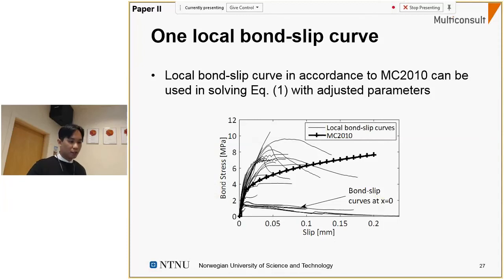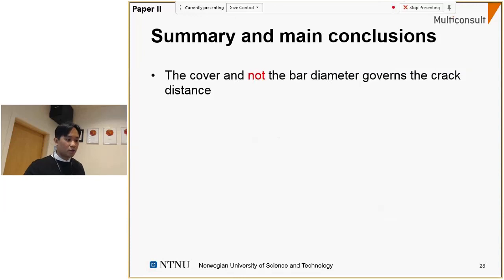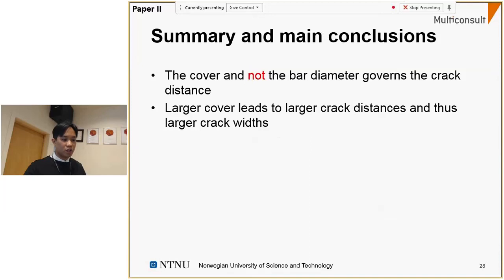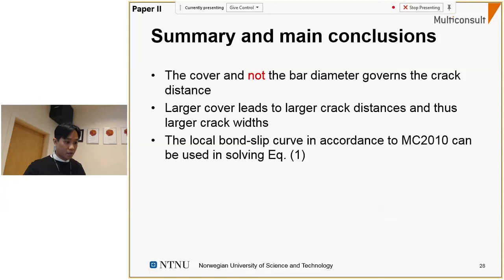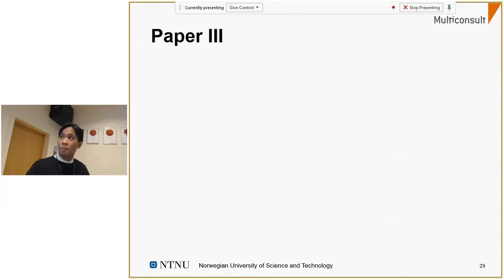I won't go into what a local bond slip curve actually means here, but it says something about how the bond stress transfer, or how the bond transfer, is affected by the amount of internal cracking in the specimens. So to summarize and conclude here, the cover and not the bar diameter governs the crack distance. Larger cover leads to larger crack distances and thus larger crack widths. And the local bond slip curve in accordance to FIB Model Code 2010 can be used in solving differential equation 1.